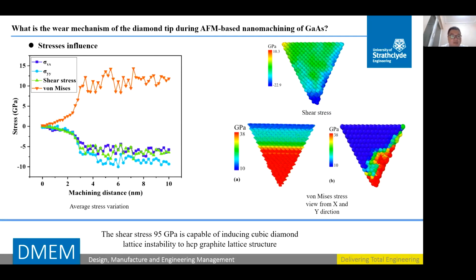On this page, the average shear stress was computed against the machining distance as shown. It was found the average shear stress fluctuated at a magnitude of 7 GPa. Additionally, after a cutting distance of 10 nanometer, the peak shear stress was mainly located at the apex of the diamond tip. The magnitude of strength was much lower than the shear stress of 95 GPa that was required to induce cubic diamond lattice instability to a graphite lattice structure.